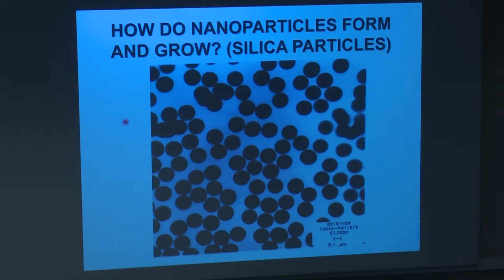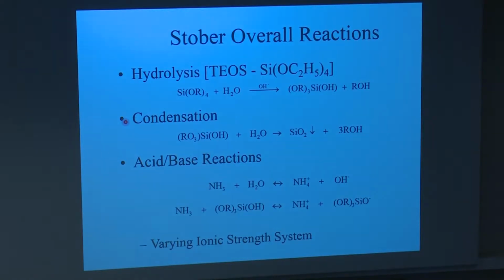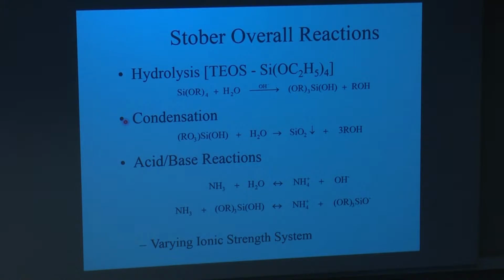And another group used cryo-TEM to show that the first particles were about 20 nanometers in diameter. And so that debate kind of went on for a while, and then I came on the scene and decided, well, let's look at the hydrolysis of the TEOS and condensation of the TEOS and see what species we can detect using 29Si NMR. And what we found is, sure enough, what you see is